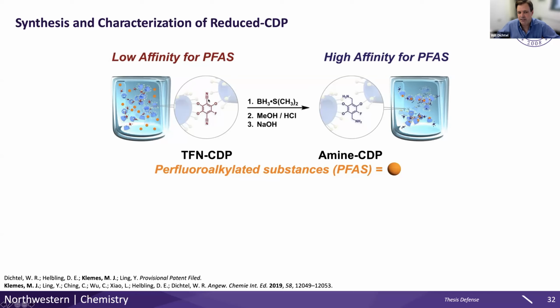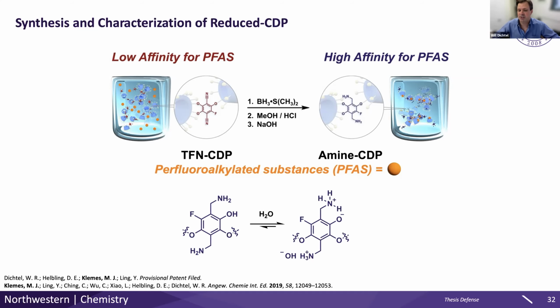And Max found a way, he adapted a way to add some hydrogens to those nitrogens, so a process called reduction. And these NH2 groups will actually pick up another hydrogen from water and become positively charged when the material is in water. So that allows us to then look at the effect of what is essentially the same material, but all we did was change the negative charges into positive charges. So great control experiment, but also potentially really, really, really nice for technologically.